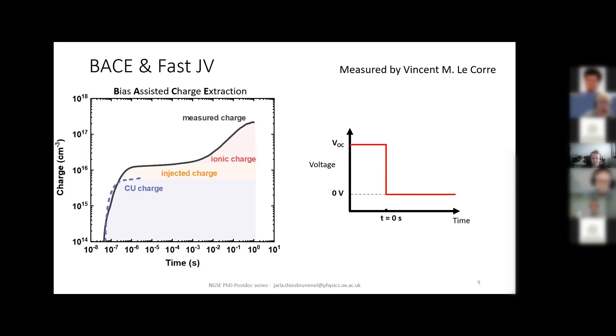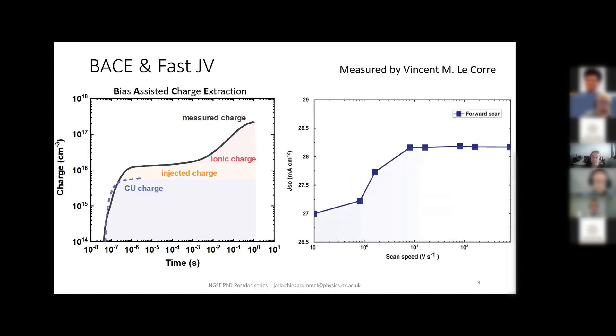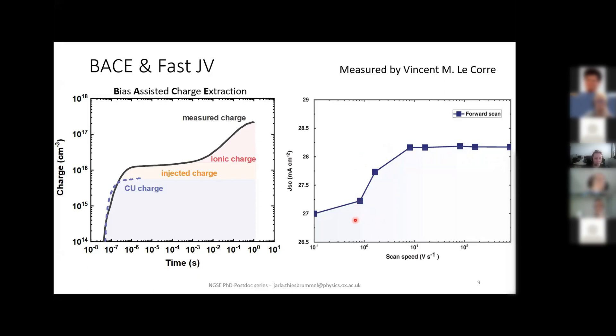To confirm this further, we also performed fast JV measurements, scanning at different scan speeds. At high scan speeds we have a high Jsc, but as we scan slower and slower, at some point there's a sudden drop in Jsc — at exactly the timescale at which the ions are moving. This means that when scanning slow enough, the ions have time to move to the interfaces and start screening the fields. So evidence is stacking up against these mobile ions as the cause of our current losses.